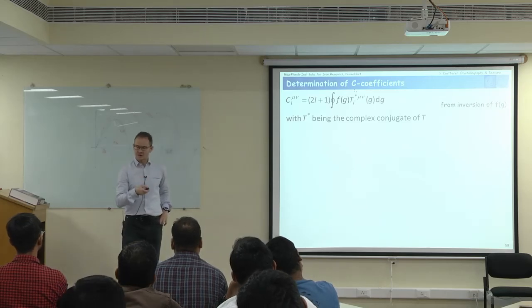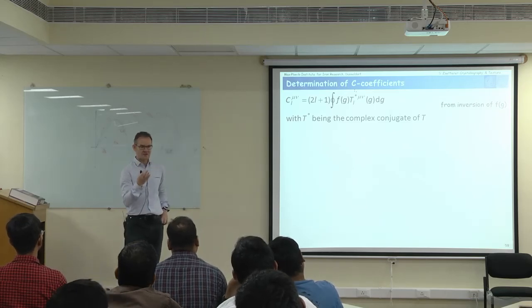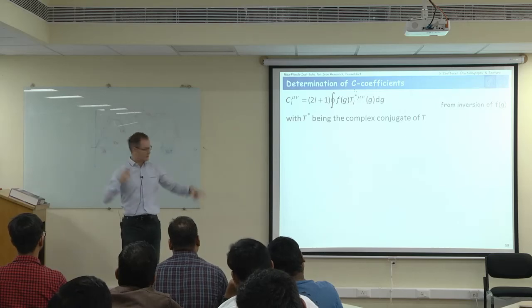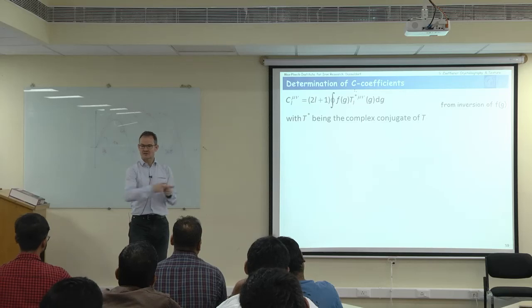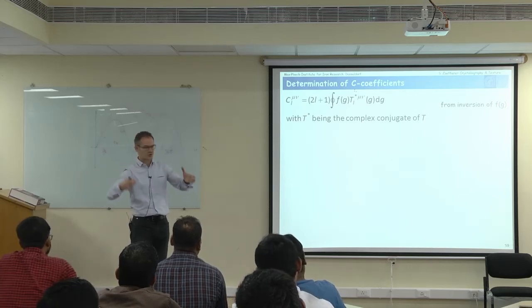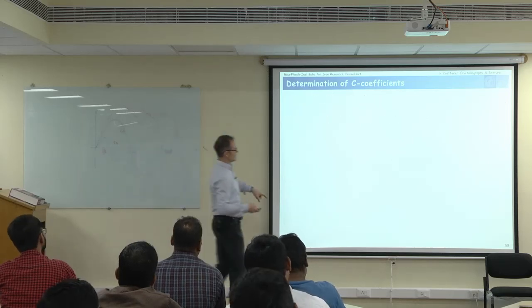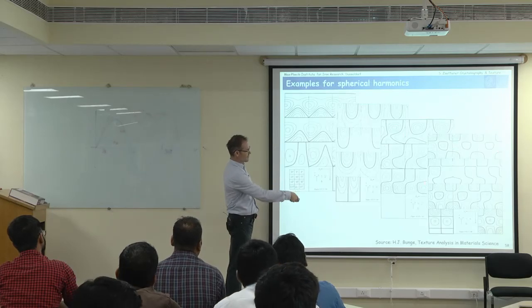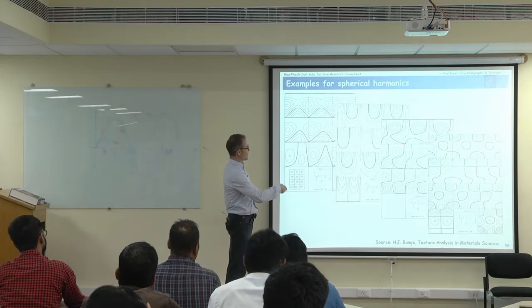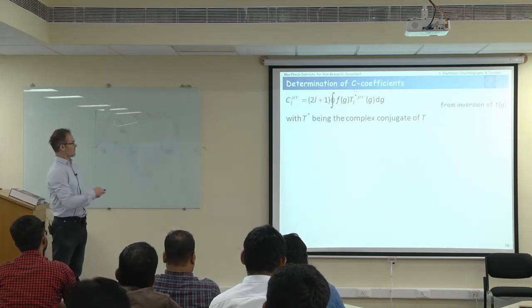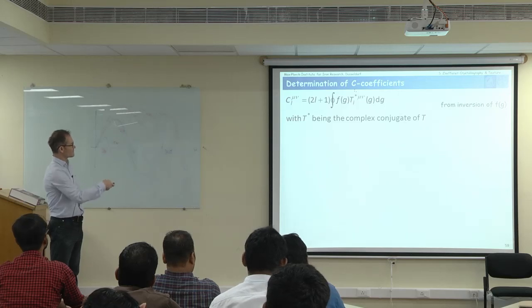The basic idea, when you do texture analysis or when software does it for you, is to find out the weight factor of all these individual contributions. So once again, how much volume percent of this do I need, how much of that, and of that. There is mathematics behind it to calculate these.